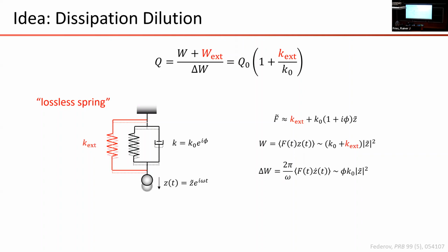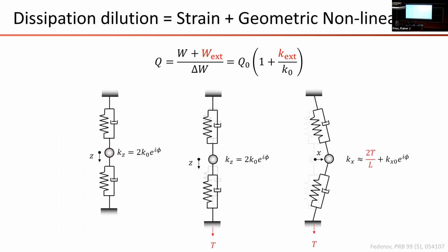And then in this model, the increase in the Q would be equal to the ratio of the effective stiffness of that conservative potential to the intrinsic stiffness. You can actually engineer this situation using tensile stress. One way to think about that is a very simple two-spring, one-mass system: a mass suspended by two springs between two fixed surfaces. One thing we know from simple classical mechanics is that if you look at the translational mode of this system, tensilely stressing it doesn't change the frequency. If you stretch a string, it doesn't change the stiffness of the string if it's a linear string.